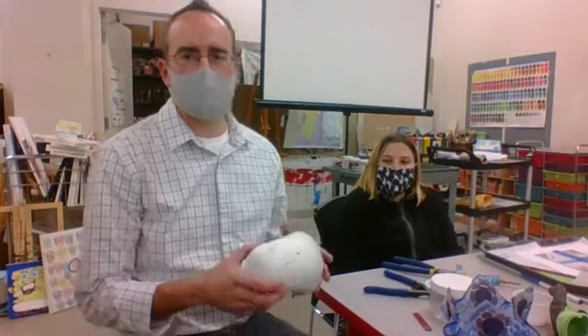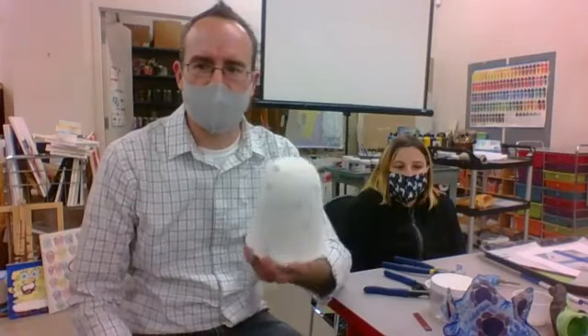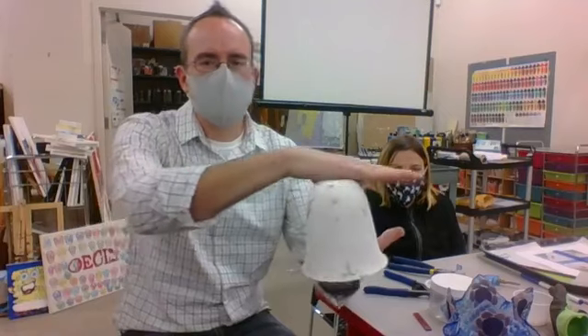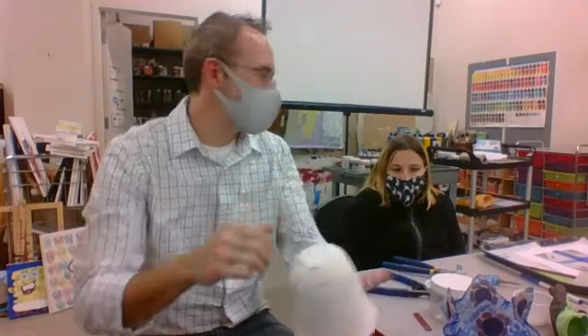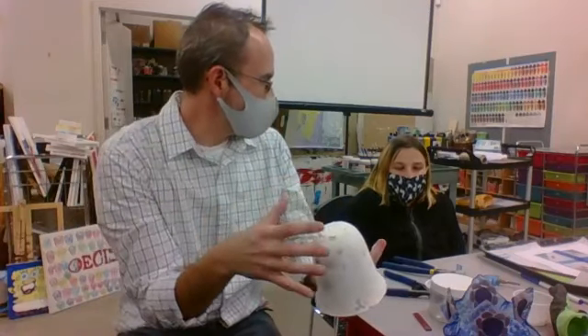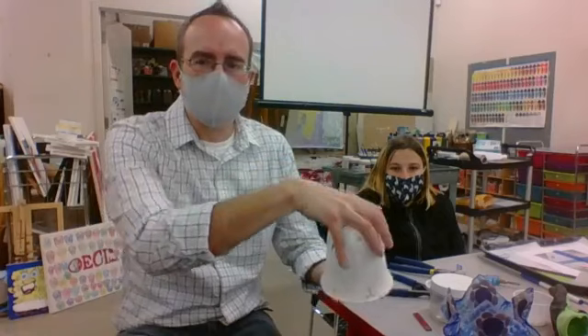After that cools and comes out, we'll clean it and then put it onto what's called a slump mold. Different slump molds can be made out of different materials. Some are made out of high fire porcelain. This one is made out of metal. Then we coat it with a nice protective covering, that way the glass doesn't fuse to the actual metal mold. The glass will just sit flat right on top. Then we take it up to what's called a slump fuse level, which is about 1250 degrees. At that point, the glass starts to bend. It gets soft, but not enough to fully melt or fuse together. So we just soften the glass at a lower high temperature, and then it molds itself into the shape and falls around it.